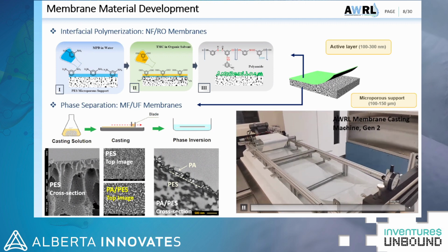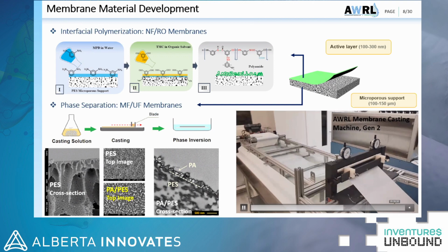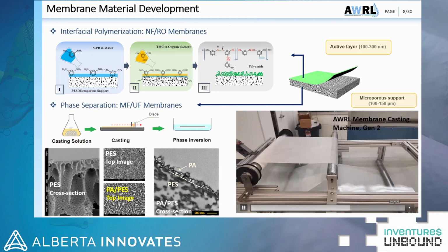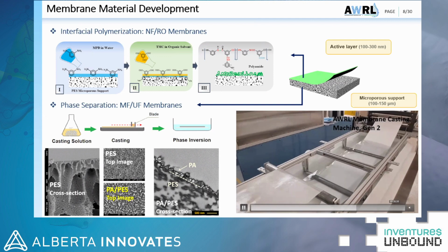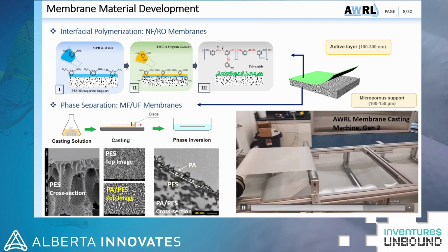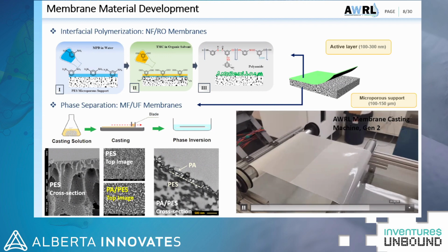As you can see, the visible pores of the PES support are covered by the polyamide layer with the ridge and valley structure. You cannot see the visible pores that we had in the PES microfiltration and ultrafiltration membranes anymore after coating the polyamide layer by the interfacial polymerization reaction, which is the typical method in industry to make reverse osmosis thin film composite membrane.